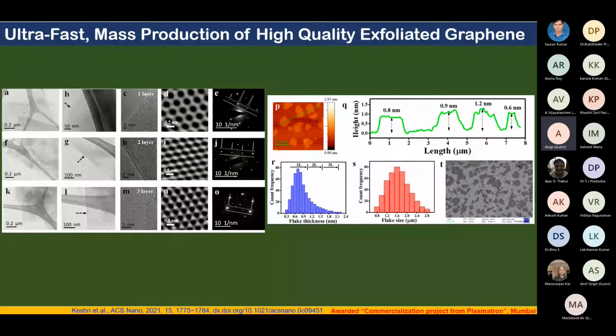To understand this, we did an exhaustive analysis using AFM. On the right hand side, image P shows the AFM imaging of this powder particle and all the flakes. Along this dotted line we plotted the thickness profile, Q, where the line passes 0.8 nanometer, 0.9 nanometer, 1.2 and 0.6 nanometer. These flake thicknesses are definitely considered as a single layer.